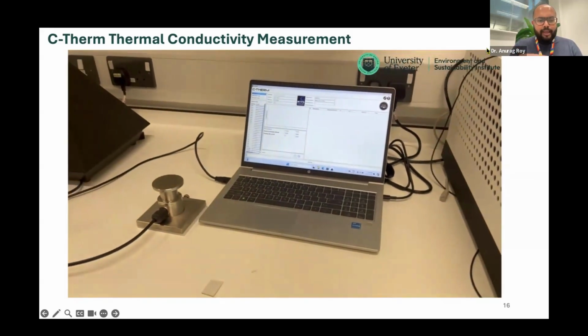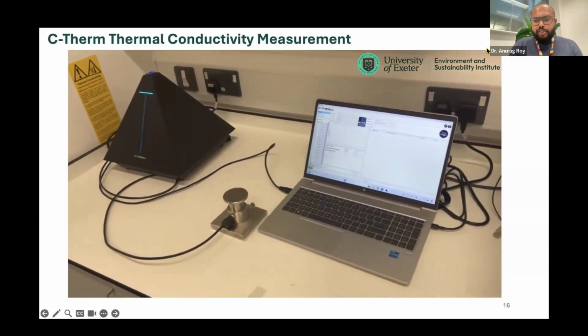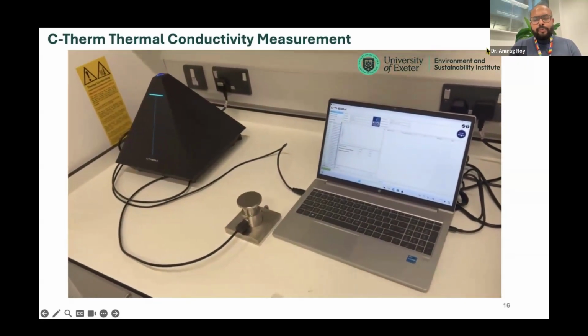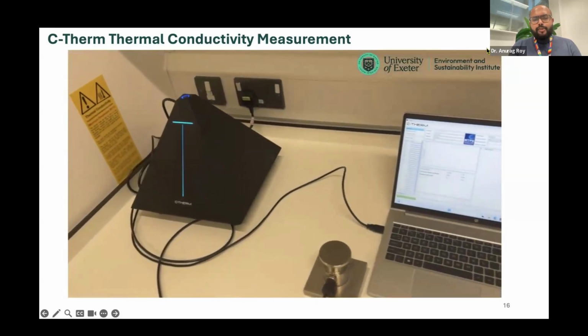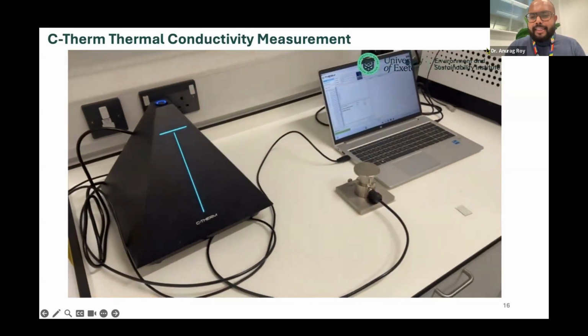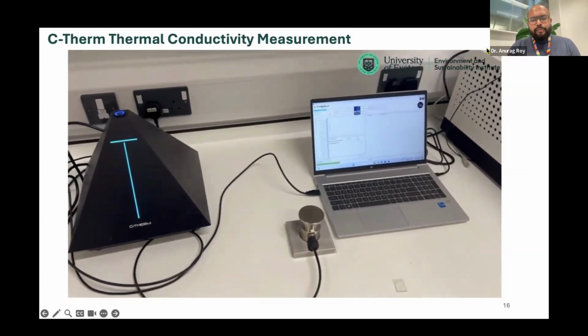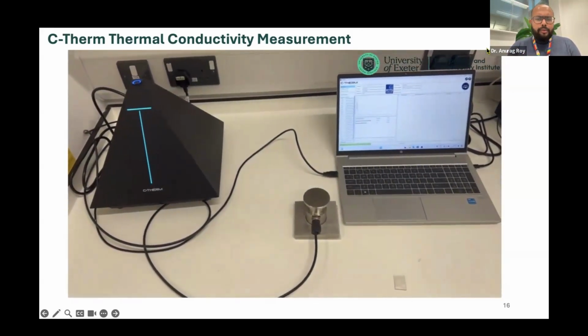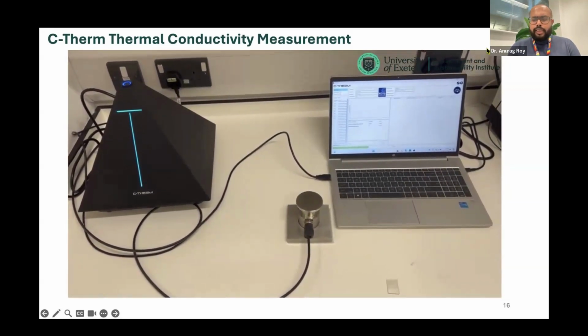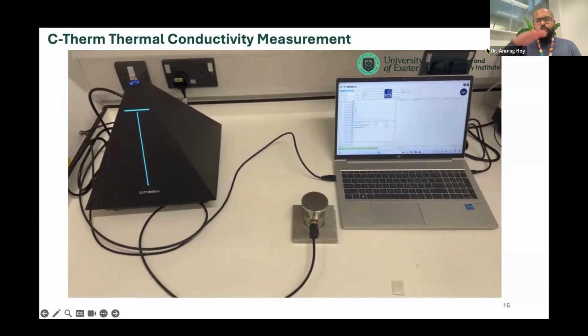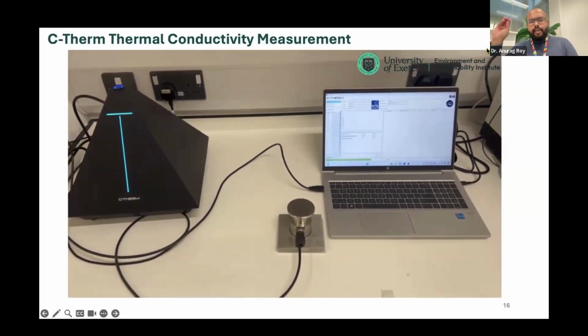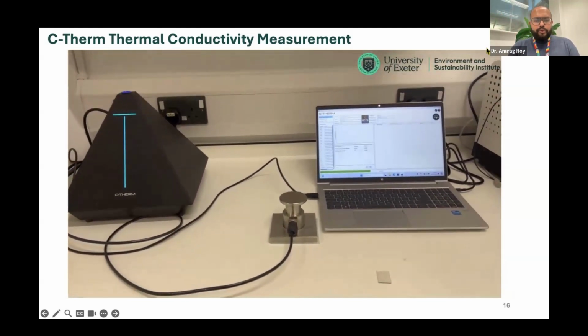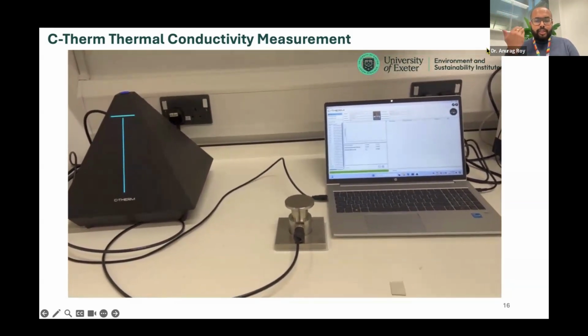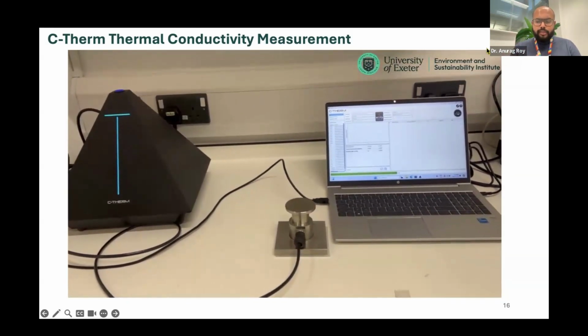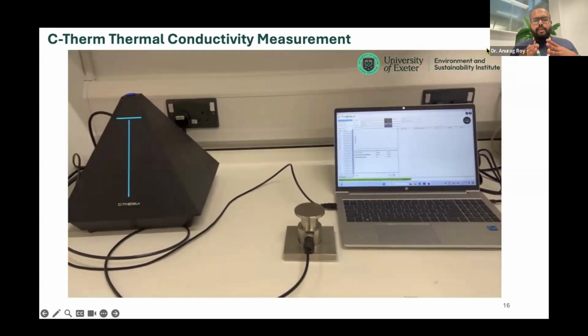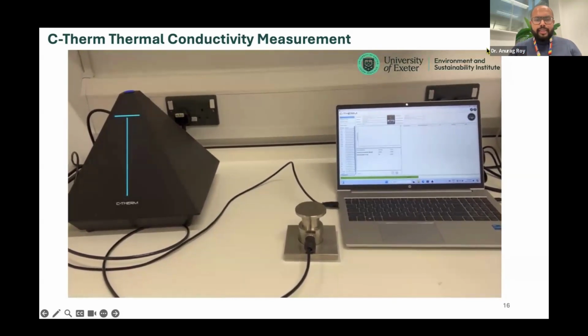As you can see, we just put the samples on with a bit of pressure and contact with water, and just turn on the instrument. The software is quite handy, and you can see there is a measurement going on. It just takes a couple of minutes, and you can measure up to 20 data points at a time, I guess, so that you can make correlations between your data and make an average out of it. Here I'm showing you only a single data point at this moment, and for comparison we always use the substrate. You can see there is FTO glass as well, so that we can understand the exact contribution from the material itself.